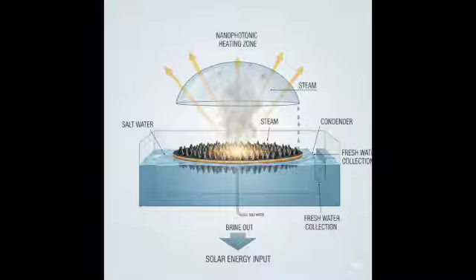What about membrane thickness? How does that play a role? Thickness directly impacts the path length for vapor diffusion. Thicker membranes mean higher resistance to vapor flow, which reduces flux. The typical range is maybe 100 to 700 microns, remember. Is there an optimal thickness?